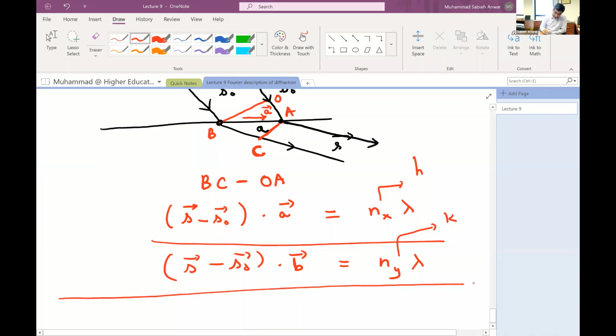So in my next lecture, what I would like to do, I would like to find out the Fourier transform of the basis. I combine the Fourier transform of the lattice with the basis, multiply the two together. I've already shown graphically or intuitively what this means. And then from the output, I would like to find out what the diffraction intensities are. And I will see that for certain Bravais lattices, certain intensities are always zero. They never show up. These are called the systematic absences.